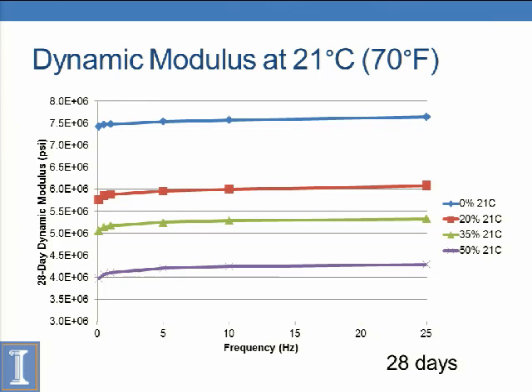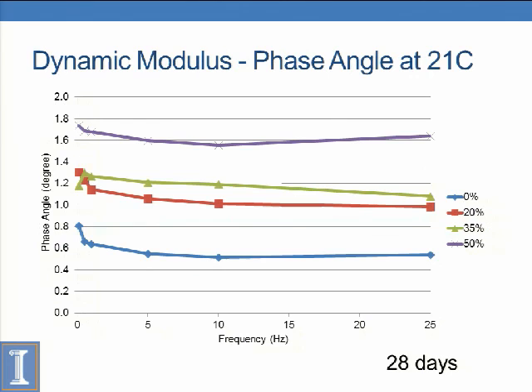For the most part, we found that it was frequency independent. There really wasn't much change with frequency, and similar with temperature. We tested at 4, 21, and 54 degrees Celsius. There really wasn't much temperature dependency either. The important thing to note is just that the dynamic modulus decreases with FRAP content.